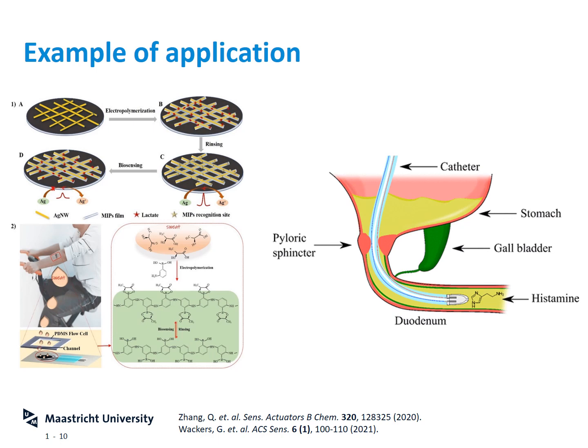Now, a different group in China, as you can see on the left-hand side, developed a patch which you can wear on your arm as sort of a hydrogel, and into that hydrogel they incorporated electrode containing silver nanowires, which they then electropolymerize with a polymer containing an imprint for lactate. They rinse the polymer out to remove the lactate, and then they attach the extracted MIP covered sticker onto the arm of a sporter, and when this person is sporting and sweating, the sweat will be transported to the patch into the electrode, and there you can read out how much lactate a person will produce during sporting, which will massively help in studying lactate formation in exercising sporters, and will probably contribute in the future to a more personalized version of training Olympic athletes, for instance.